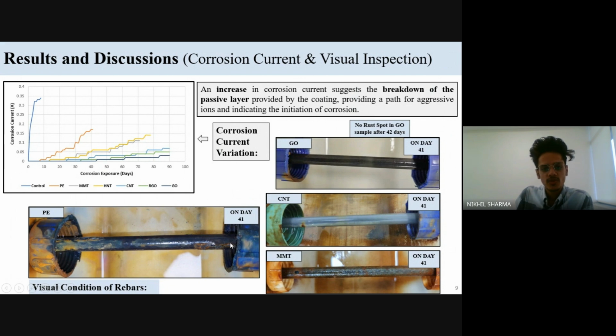In the visual inspection, we can see, for example, in 41 days, plain epoxy coated rebar is severely corroded, and we can see the coating has white cracks around the surface. Whereas in GO, in 41 days, there are no corrosion spots, and in CNT and MMT, we can see several corrosion spots.